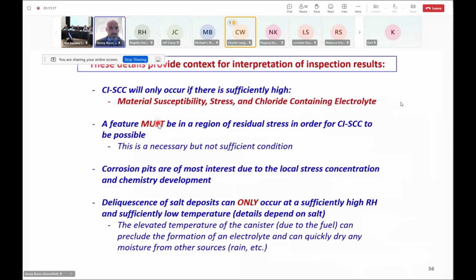So let me briefly align this talk and finish up with: why did I talk about these things? I think these details provide context for interpreting the inspection results. CISCC is only going to occur for sufficiently high material susceptibility, stress, and chloride-containing environments. A feature must be in a region of residual stress for CISCC to be possible, but being in that region is necessary, not necessarily sufficient. Just because you find an indication inside a weld region does not mean you're going to have CISCC. You would also need a sufficient level of stress and an electrolyte.